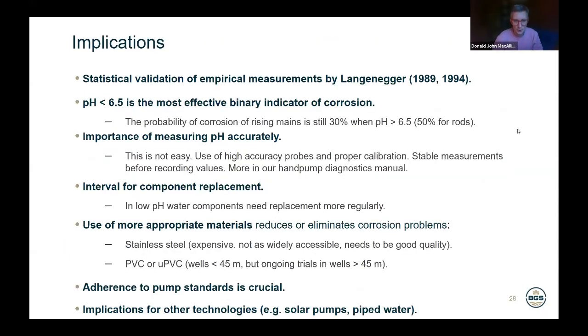So what are the implications of all this? Firstly, we've produced strong statistical validation of the empirical measurements that were done by Langenegger. We've really backed up that work that he did in the 80s and the 90s. We've shown that pH 6.5 is a very effective indicator, but that actually, when your pH is above that, at least 30% of our observations still found corrosion.